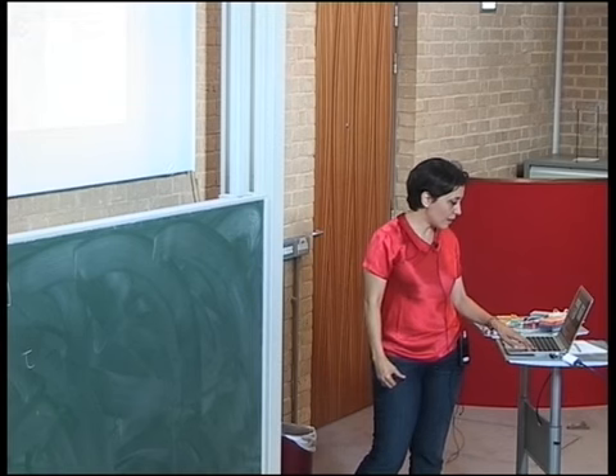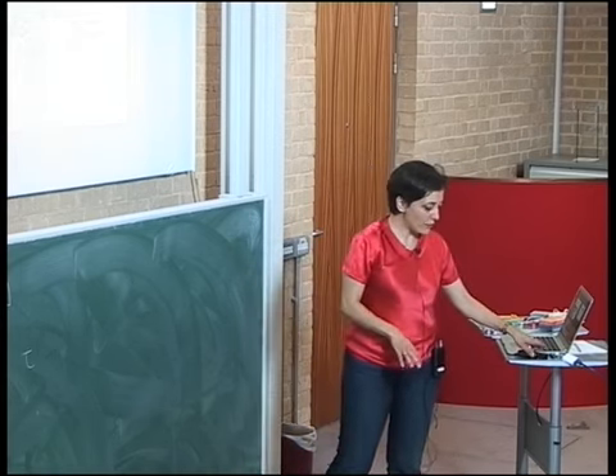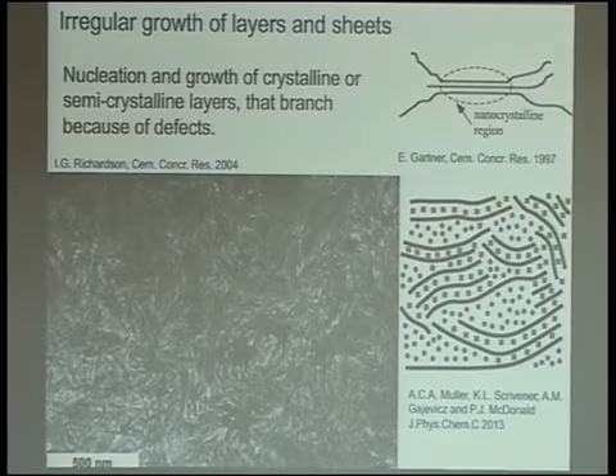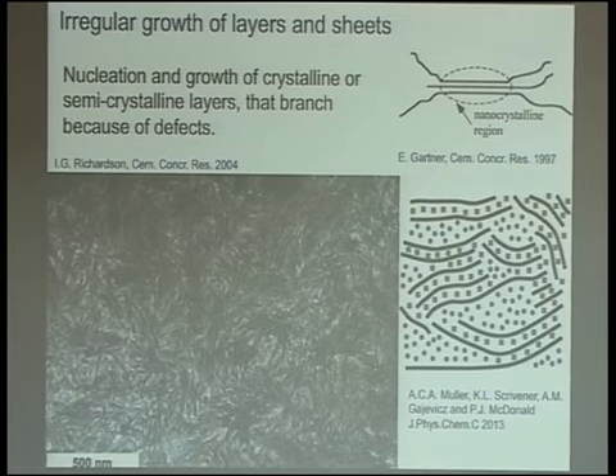An alternative picture is based on the idea that during precipitation you form elongated structures, which are ribbons or sheets, and then these branch due to the defects that are produced during precipitation, and this branching of these elongated structures is what produces the mesoscale disordered organization of the gel. In fact, this model is really just a picture. It's never been quantitatively tested, but you can trace a number of characteristics of this type of picture in the images and in other.